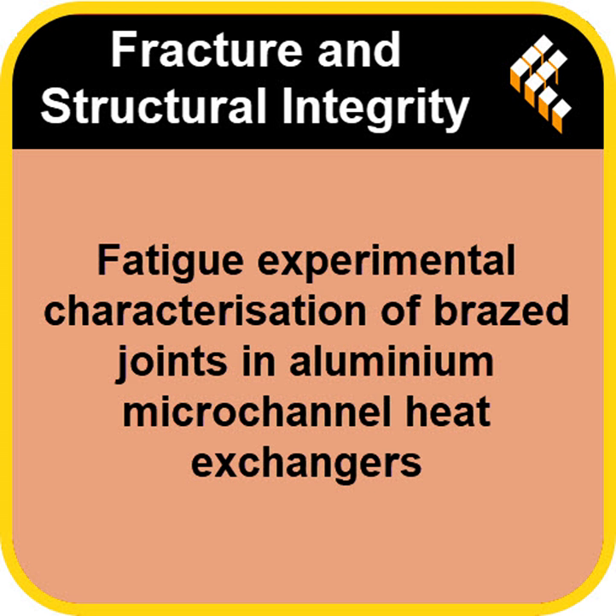No more guessing. So that FEA work then guided the physical testing phase. They designed a special fatigue specimen that accurately replicated this critical joint geometry and, importantly, the stress field identified by the model. Then they started hitting it with cyclic loads. Right, uniaxial cyclic loading. Pulling and releasing, millions of times. They used a standard stress ratio, R equal 0.1, a frequency of 20 hertz, and their target was 10 million cycles. That's often considered the threshold for effectively infinite life in these kinds of applications.